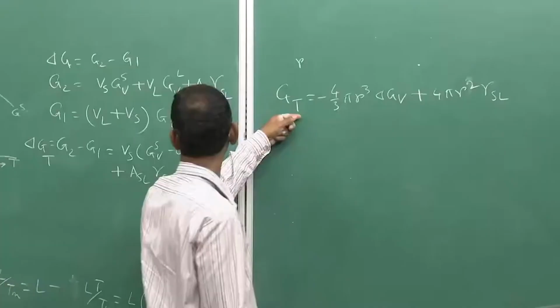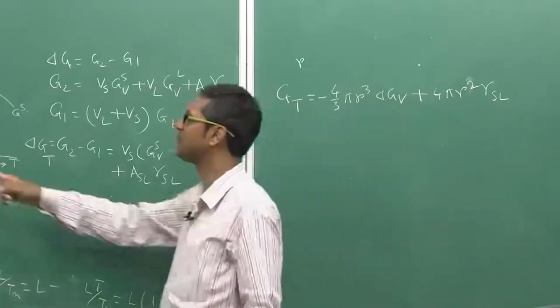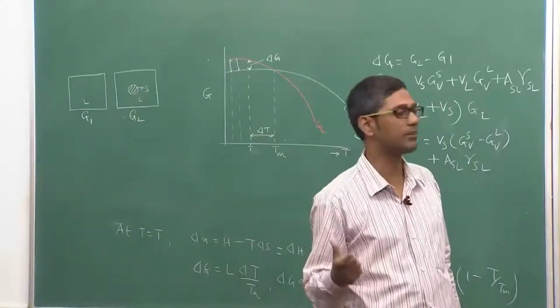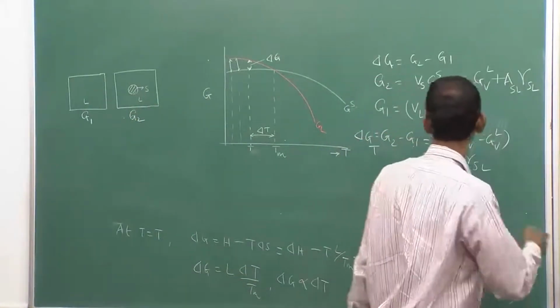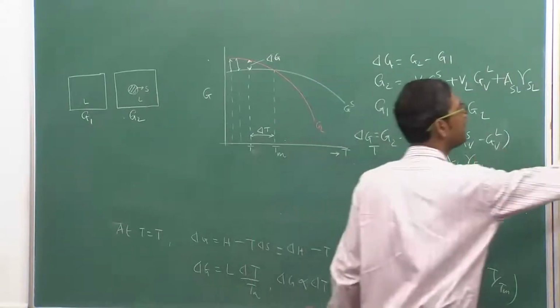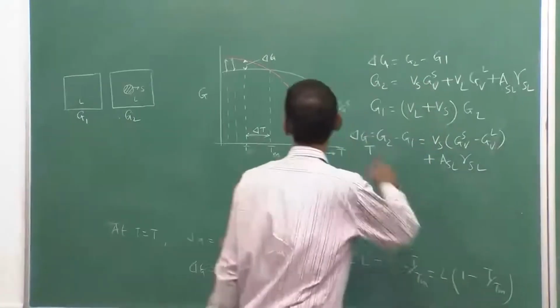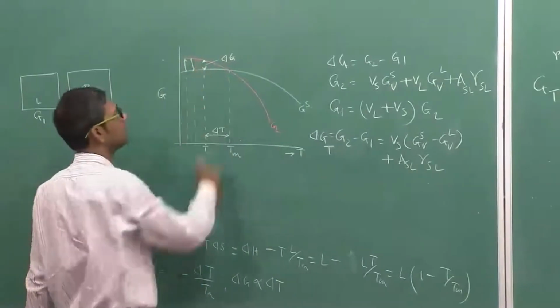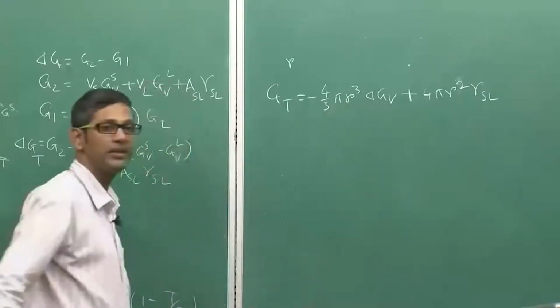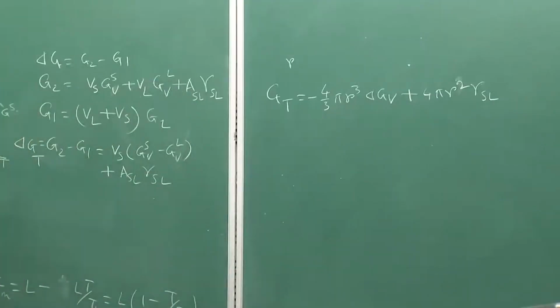So what I have done here, same thing in this equation, I have assumed this particular species which is formed out of liquid is nothing but a spherical shape. If I have a spherical shape, then I write this delta G V, solid minus liquid, therefore this will be negative, and V is 4/3 pi r cubed, that is the volume of the solid piece.